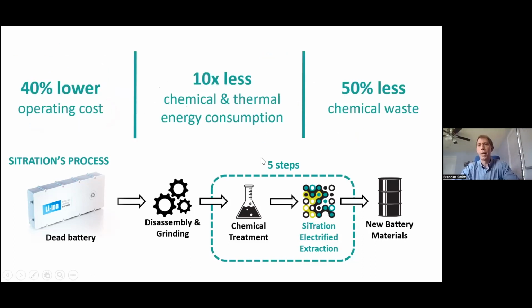In terms of the quantification of the impact economically and sustainability-wise, the top three cost drivers of the process, talking to all the stakeholders that we know of, are really chemical inputs, thermal energy inputs, which are very inefficient energy-wise, and the chemical waste treatment cost. And SiTration is substantially impacting all three of these. We see an 80 to 90% reduction in chemical and thermal energy inputs in our process compared to the status quo, and subsequently also about a 50% reduction in the volume of chemical waste that's treated at the end of the process. So when you plug this into some detailed techno-economic modeling, what you see is a conservative estimate of about 40% reduction in OPEX relative to the status quo. So this is very exciting, not just from a sustainability perspective, of course, but also from an economic perspective. And it's very important, of course, that these two things are aligned to be able to implement solutions like this industrially.